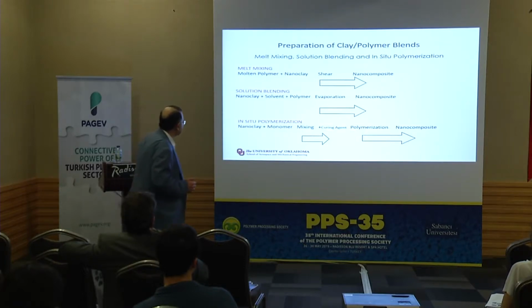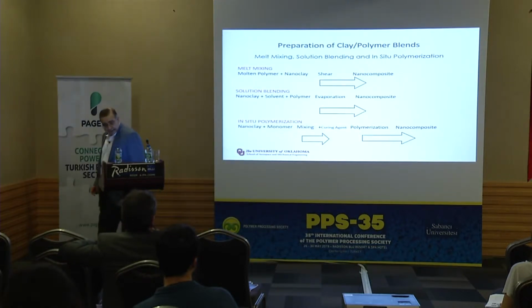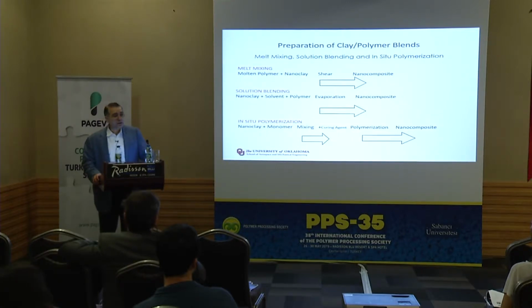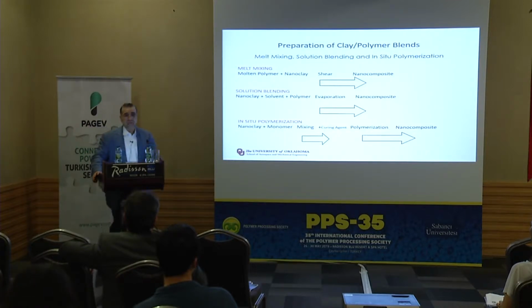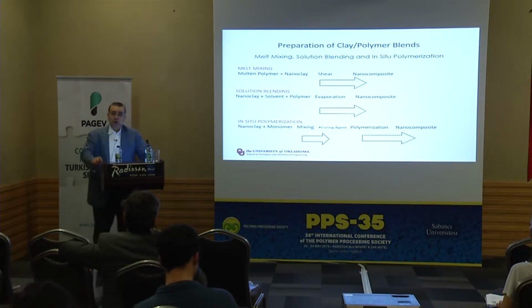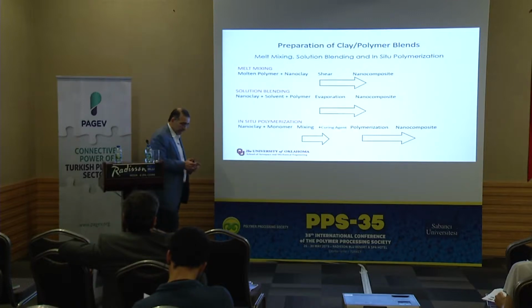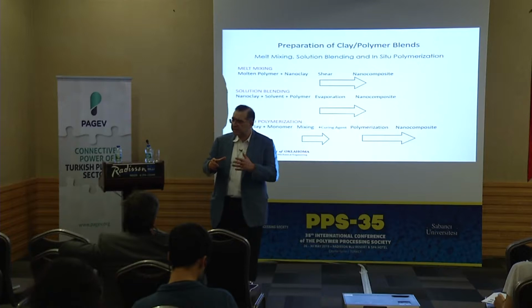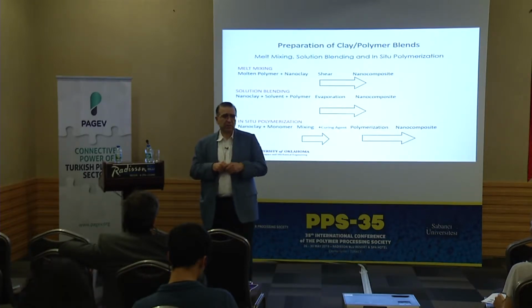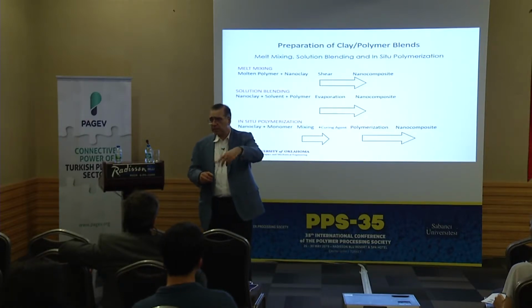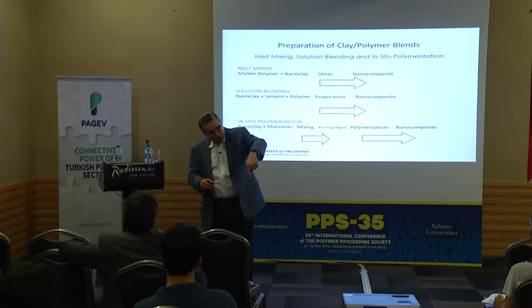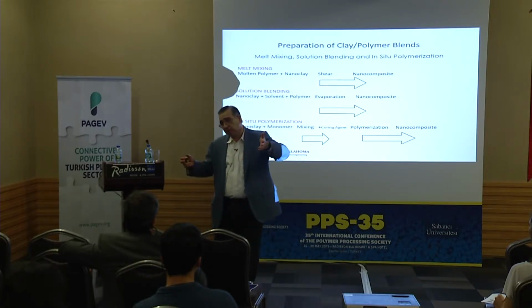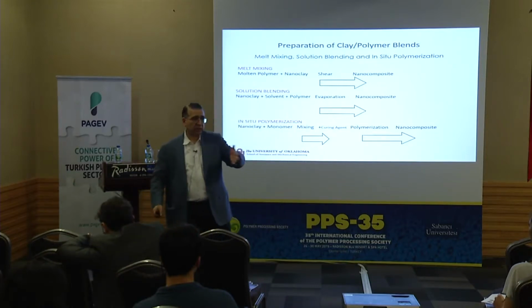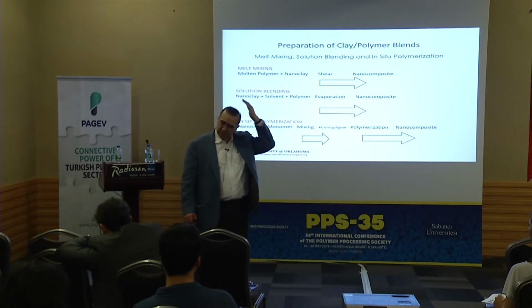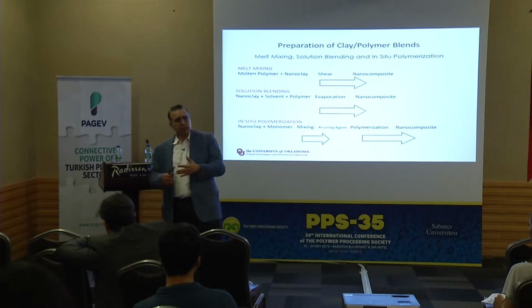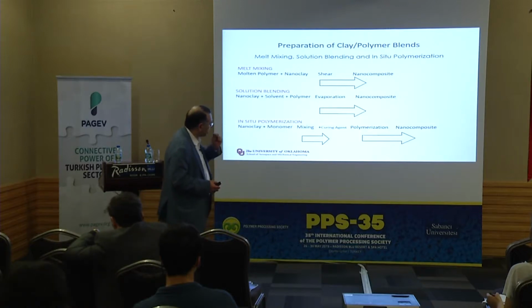In situ polymerization is another way to add clay. Another very common way is sonication. If you look at the literature of the last 10 years, there would be several hundred articles that use sonication. In sonication, you have either a bath sonicator. Bath sonicators are commonly used in labs to clean things, right? So you put the liquid resin, maybe thermosetting, epoxy type, with the clay, and sonicate. Or you use a tip sonicator with a probe, so you dip it in, and sonicate maybe 1 minute, maybe 10 minutes. The reports range from 1 minute to 60 minutes. But we looked at the results, and you achieve most of the dispersion within the first 10 minutes. So that is another commonly used way, tip sonication.